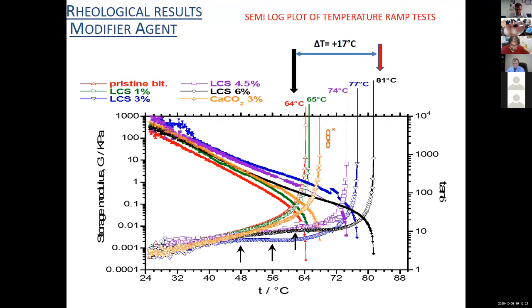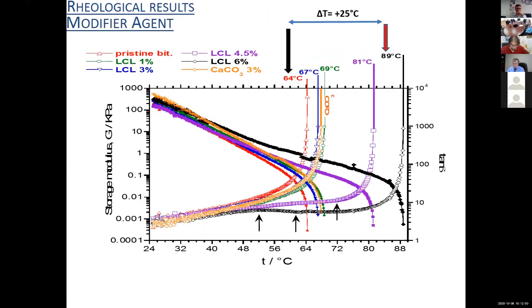In general, a good modifier agent increases the transition temperature of the bitumen. We observe that the transition temperature increases with the percent of additive, and we see in the LCS case, the shift of the temperature is around 17 degrees in comparison with the bitumen without additive. While in the LCL case, we observe an increase of 25 degrees in comparison with the pristine bitumen.